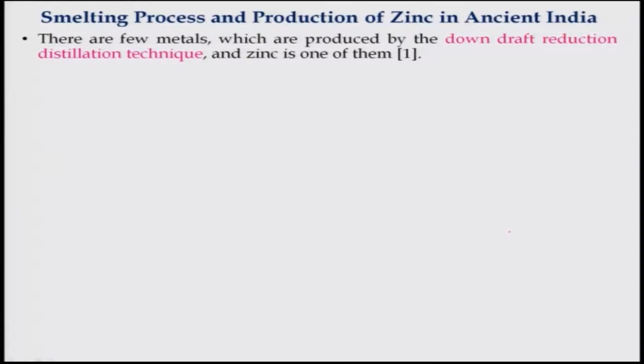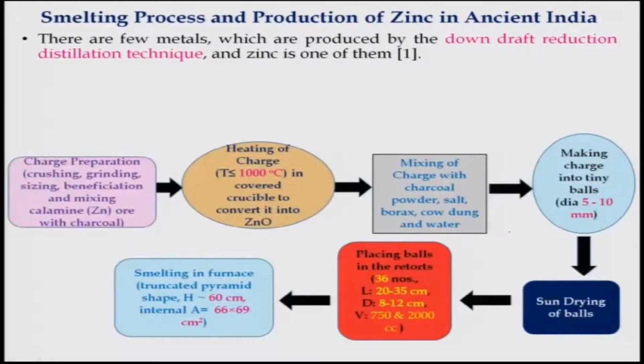So, let us look at the smelting process and production of zinc in ancient India. As I mentioned earlier, there are a few metals which are produced by the downdraft reduction distillation technique, and zinc is one of them because its boiling point is very low. What is done in this case is that the charge is prepared. For preparing the charge, the ore has to be crushed, ground to the proper size, and beneficiated, and then you mix the calamine or zinc ore with charcoal, put it into a crucible, cover it and heat it to around 1000 degrees Celsius.